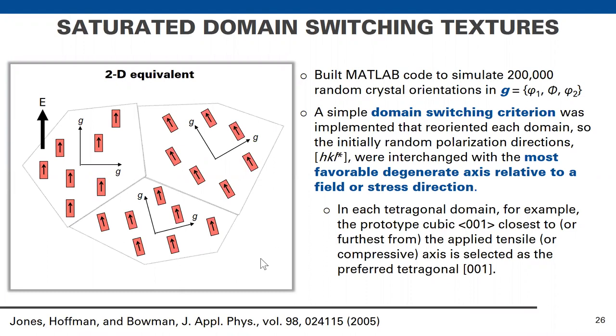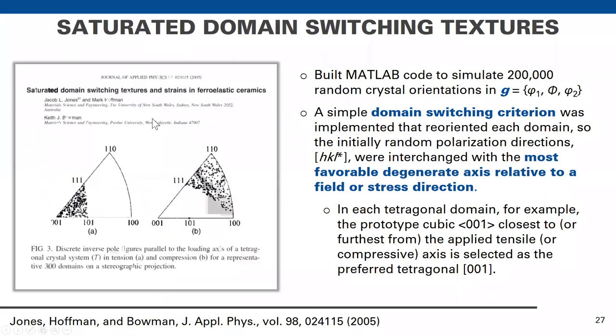Okay. Now that's a very simple switching model, and a mechanics person would probably laugh at it, but it's very useful for describing the orientation dependence of some of these effects. And so we built this model using about 200,000 random crystal orientations. We implemented this switching criteria, which determines the most favorable degenerate axis relative to the field or stress direction. And we started getting some interesting results. So the paper that reported it is shown here. I show an inverse pole figure, which represents the different types of crystallographic directions that are parallel to a sample direction. And so this one in part A is parallel to the electric field direction. So in a fully poled or fully saturated case, these are the possible crystal directions that you would have represented parallel to the electric field.